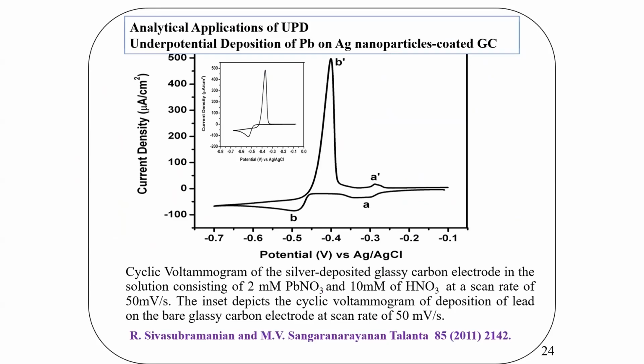You can also use it for sensing, let us say, nanomolar amounts of various compounds. Here you can see what we have done is we coated silver nanoparticles on glassy carbon. Then we studied lead under potential deposition, which is here. Whereas if I don't have silver nanoparticles and I study lead on GC, glassy carbon, there is no peak here. Only when I coat silver nanoparticles on GC and study lead deposition, this peak is coming. And this I can use to sense lead ions because it's a reversible process. I can do stripping of the lead ion in the solution, and I can exactly get the amount present in an unknown solution of lead ions.